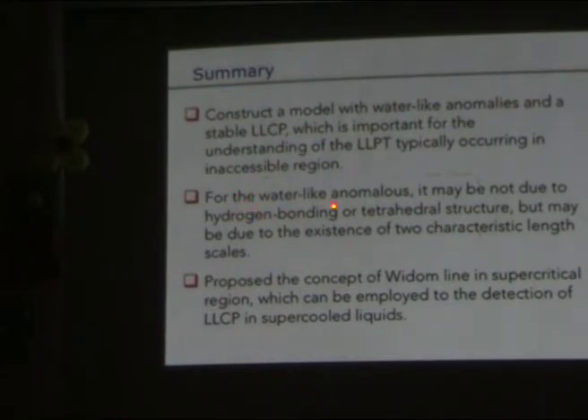The second one: because this model is not water, we cannot call it water, because there is no hydrogen inside. There are also some other differences I didn't tell you exactly, but it shows all the water-like anomalies. So this means the water-like anomalies may not be due to the hydrogen bond, and may also not be due to the tetrahedral liquid, because we know from experiment that water, silicon, and germanium all share similar anomalous behavior. The other thing they have in common is their structure, the stable tetrahedral structure. But in our model, the stable structure is the BCC structure.